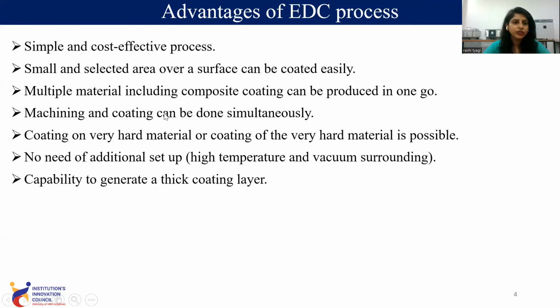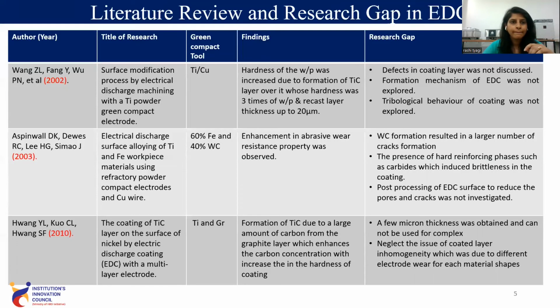surface characteristic during machining. Coating of very hard material is possible. It means any hard material can be used in this setup. Basically, no high temperature vacuum surrounding is required as it is required in other processes such as laser cladding process or any other process. Capability to generate a thick coating layer. It means you can generate thick coating layer up to 2 mm thickness. Even if you want to repair the component, you can deposit the thick coating onto the surface.